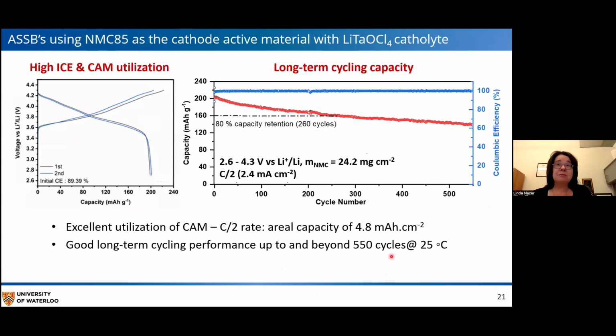And this works perfectly well as a cathode up to about 4.3 volts. We have areal capacities attained up to 4.8 milliamp hours per square centimeter and good cycling performance up to 550 cycles at 25 degrees. I might add that this is not quite as good as we see in the case of the halides, but these cells are under a lower pressure.